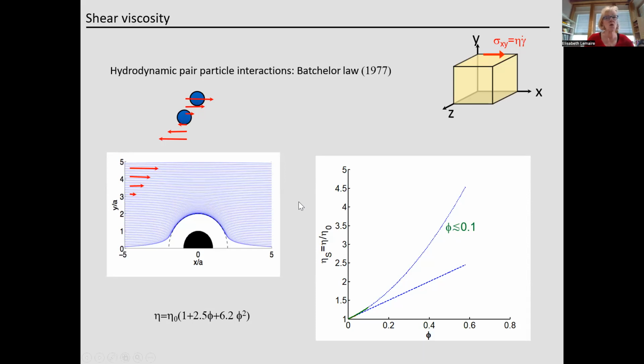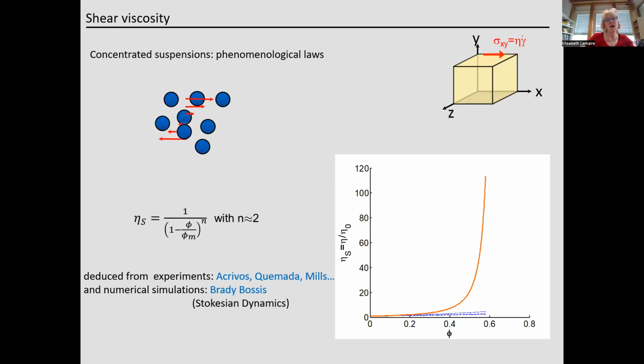And if you increase again the particle volume fraction, then you do not have any theoretical expression for the variation of the relative viscosity with the particle volume fraction. And you have to refer to phenomenological or semi-phenomenological laws deduced from experiments and also from semi-quantitative arguments. For instance, it's the case of the laws proposed by Krieger, Quemada and Mills. The laws are based on semi-quantitative arguments. And you can also refer to experimental results. And for instance, Andreas Acrivos has done a lot for the understanding of suspension rheology.